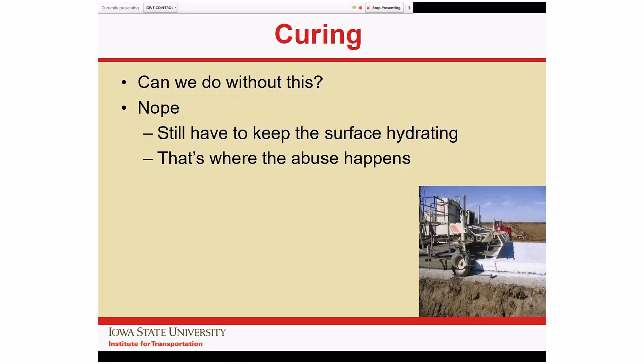Does it mean we can do away with conventional curing? And the answer is preferably not. The internal curing will reduce the rate of drying at the top surface, but on the other hand, it doesn't stop it. So from my point of view, it is still a good idea to keep the surface from drying out prematurely. We need to have either a burlap, a flooding, and or a sprayed curing compound system to get belts and braces to get everything running properly.